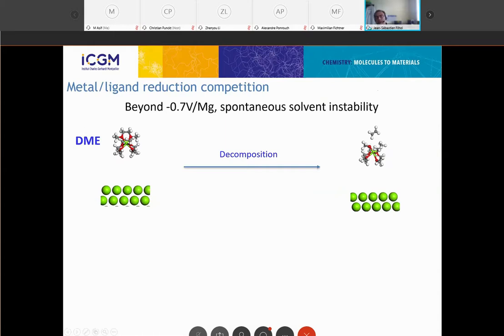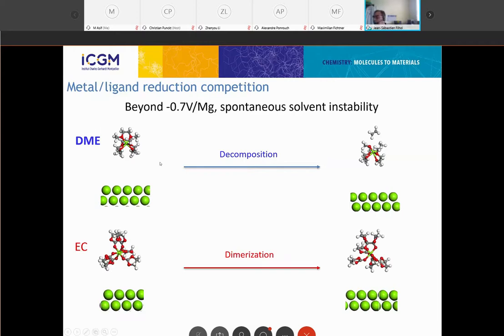methanolate, magnesium dimethanolate at this potential. So mostly that would correspond to reduction not of the magnesium 2+, but of the solvent around it. And for ethylene carbonate, we also observe spontaneous evolution, but that is this time a dimerization. We have two ethylene carbonate molecules that will just form a carbon-carbon bond with many other reorganizations in the geometry of the ring.